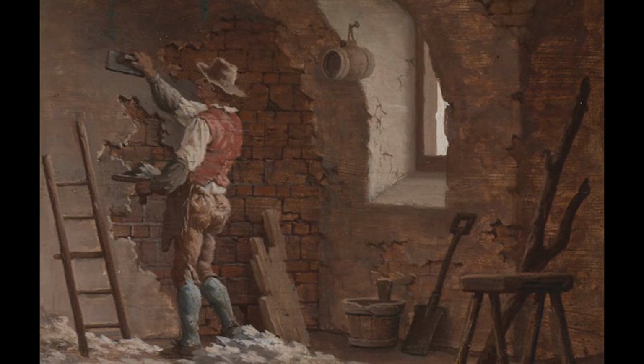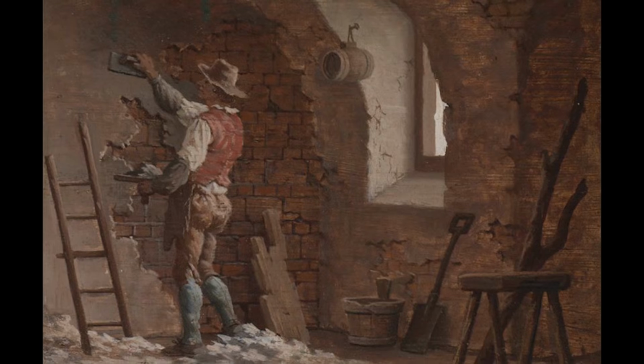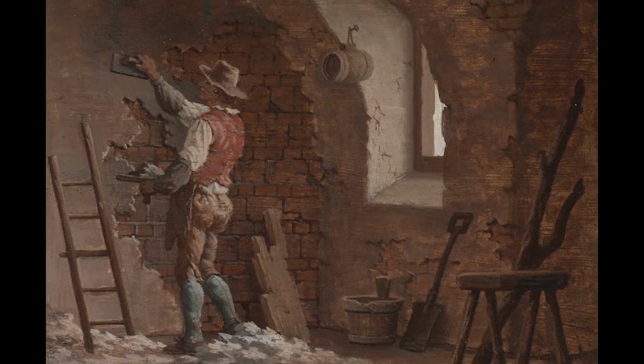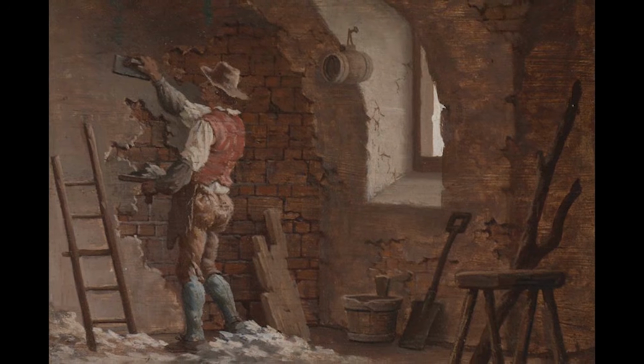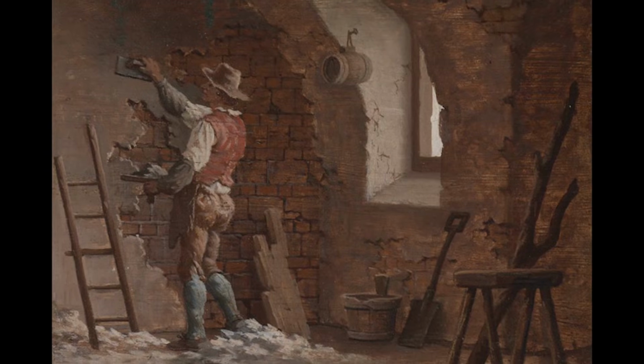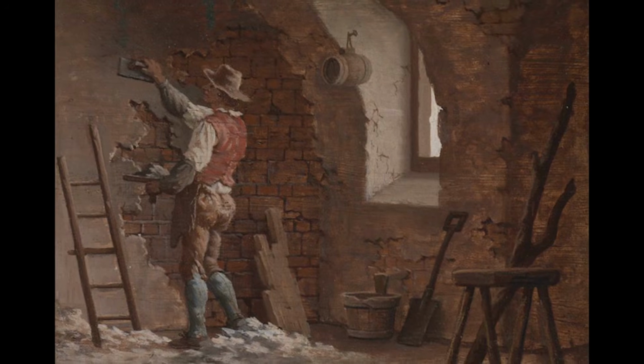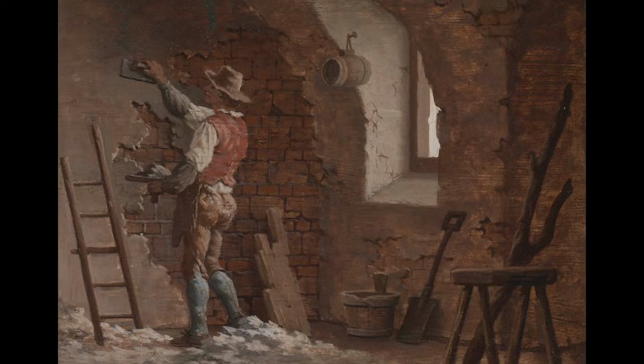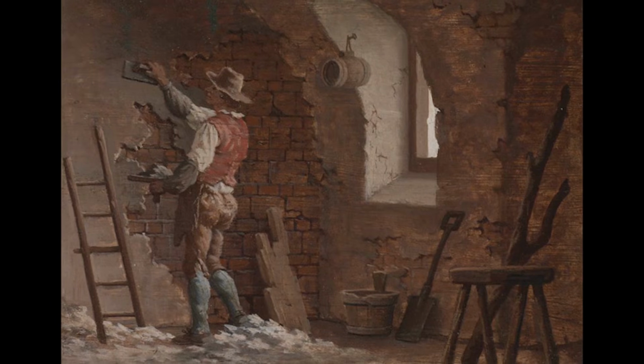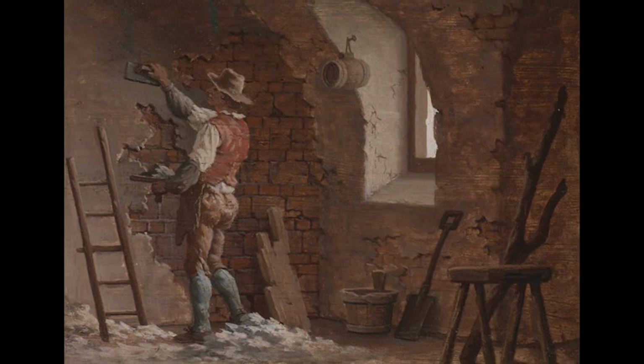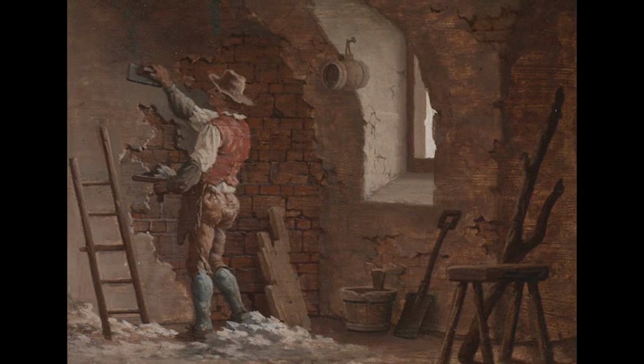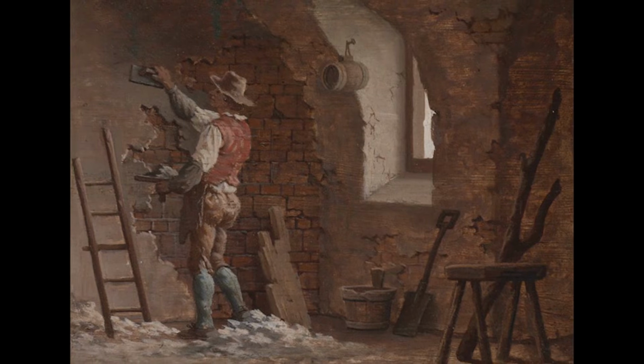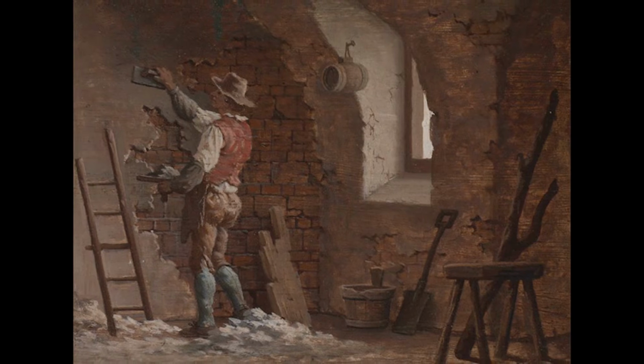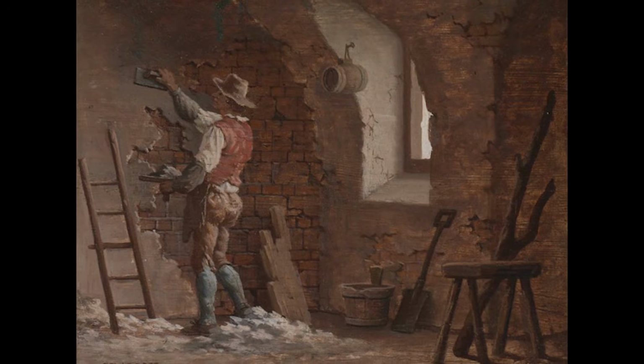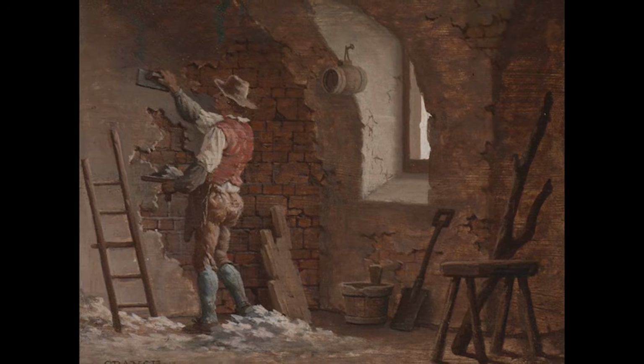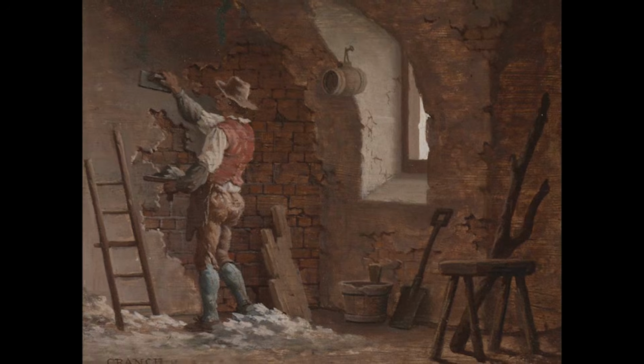What made medieval lime mortar different from modern cement was its behavior over time. Fresh lime mortar stayed workable for hours, allowing masons to adjust stones and perfect their joints. As it dried, the calcium hydroxide in the lime slowly absorbed carbon dioxide from the air, converting back into calcium carbonate, essentially turning back into limestone. This process, called carbonation, could take months or years to complete fully, gradually hardening the mortar while maintaining some flexibility.